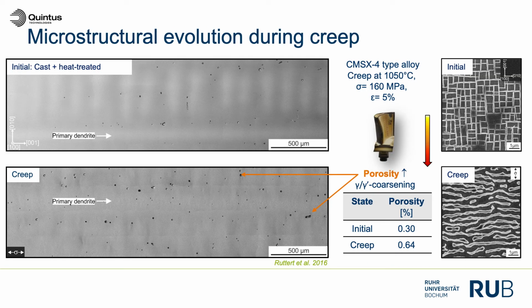microstructural coarsening. The gamma prime cubes evolve towards a directionally coarsened microstructure, the so-called rafting effect. And we can also see micropores evolving, the so-called creep porosity, or micro cracks that can form after creep or fatigue damage. And the rejuvenation has a goal to re-establish the microstructure that has been before service. And here we have done a lot of work also in the past.